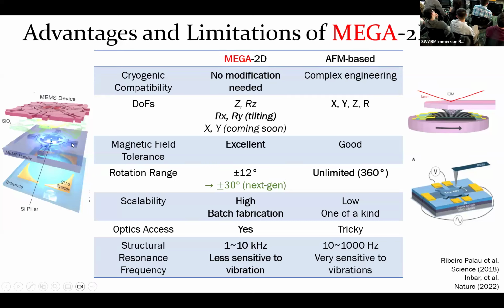With these electrostatic MEMS devices, we can achieve a range on the order of plus or minus 12 degrees for rotation. And this is plenty for studying graphene, for example. If you recall, we only need 1.1 degrees to reach the magic angle.